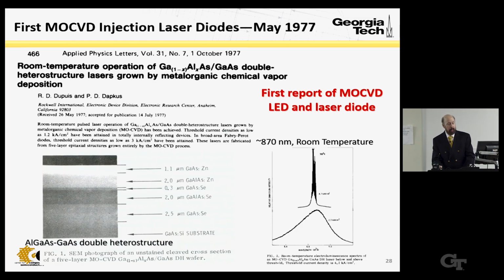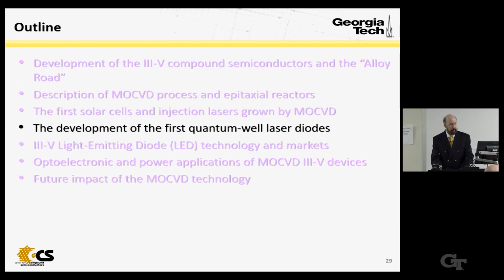They were room temperature. And this report sort of shocked the industry, because at the time, people thought LPE was the only working technology. MBE was being developed, and so there were some examples of MBE lasers. They weren't reliable, though. They couldn't meet the requirements of the Bell system in reliability. So this gave another option for developing lasers. And in fact, as I'll discuss now, the first quantum lasers. So these lasers that were existing up until about 1977 were heterojunctions with layers on the order of maybe 300 to 200 nanometers in the active layer. That was limited by LPE production technology.